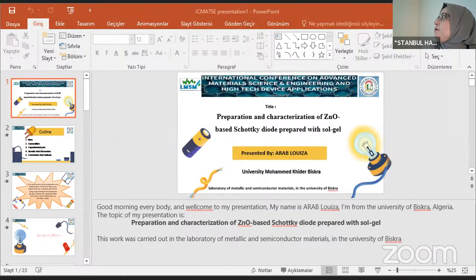The third figure shows the optical transmission spectra of ZnO thin films and the diode. Here we have used two solutions and we study the effect of time. We used the solution after it was left to rest for 24 hours, and here we have 8 days. For zinc oxide, this color and this one, the green, we notice that there is some degradation in the quality of the ZnO films. However, for the diode, this blue color and this orange one, the diode keeps the same characteristics. We have not seen much change in the characteristics of the diode.